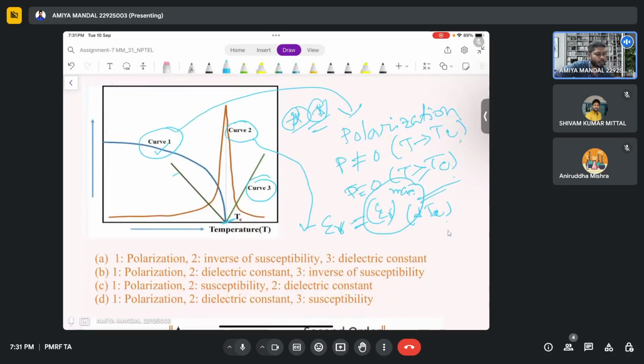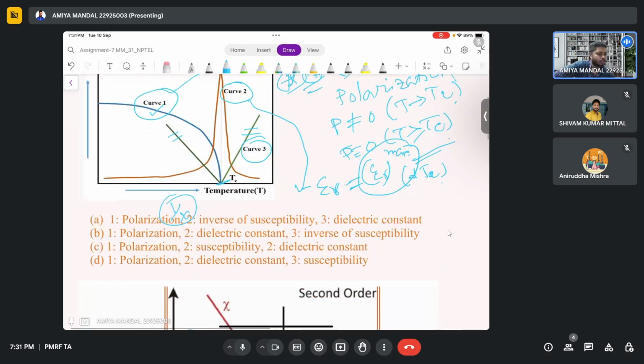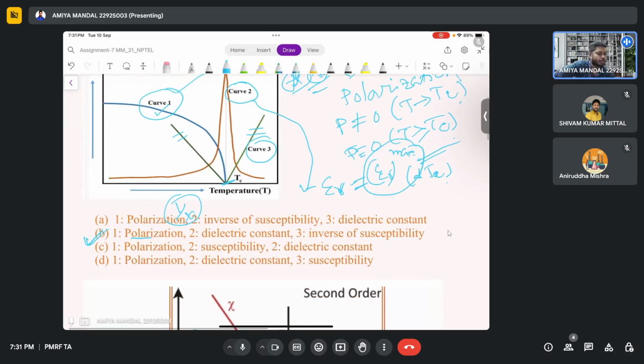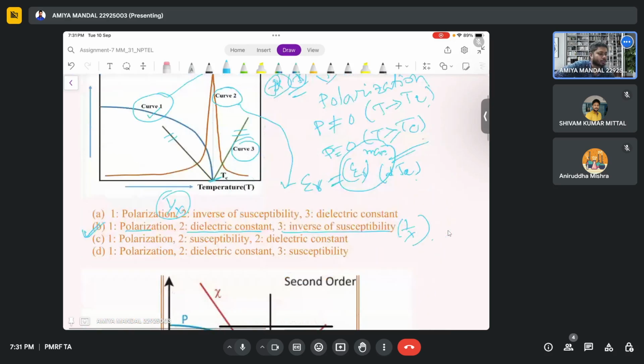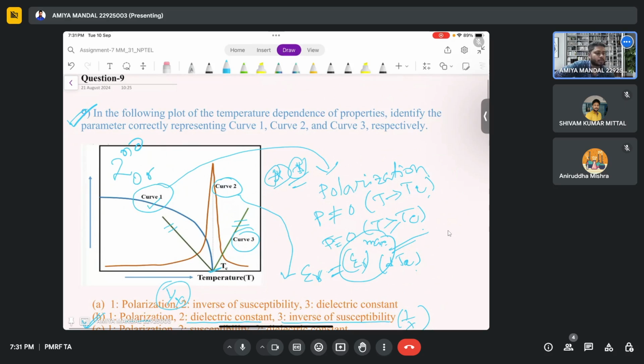And this green curve is nothing but the 1 by chi value, the inverse of susceptibility. So that should be the option 1: one is the polarization, second is the dielectric constant, third is the inverse susceptibility, which is 1 by chi. This plot is correct only for a second order phase transition. For a first order phase transition, there should be a jump at this point, a discontinuity in chi also, and the dielectric constant variation would be different. But this is the case of a second order transition.